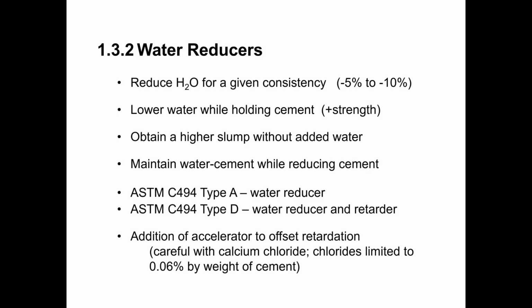If you're in a very hot environment and the concrete tends to kick off and start hardening very quickly, and you need a little bit more time to get the concrete properly finished, then using a type D water reducer may be to your advantage. On the other hand, if you're in an environment where you really want to get as much early strength as you can, then you may want to avoid using a type D water reducer and make sure that it is a type A so that you don't get any retarding effects. The retarding effects can be offset by using an accelerator. That's fine, but you are adding cost. So it may be more cost effective to just not use a type D water reducer, but to use a type A instead.